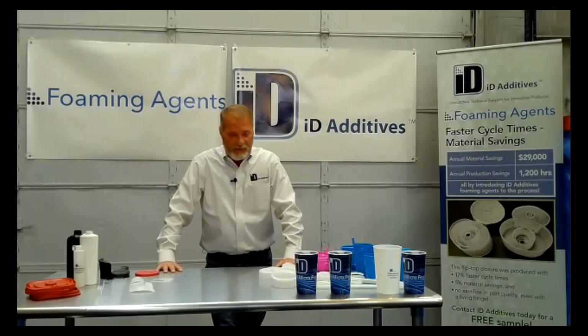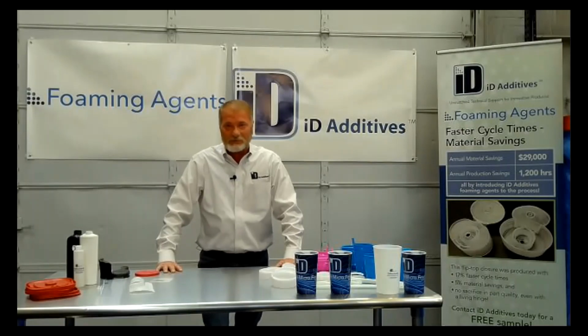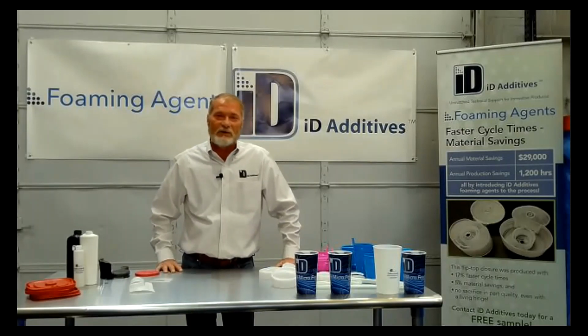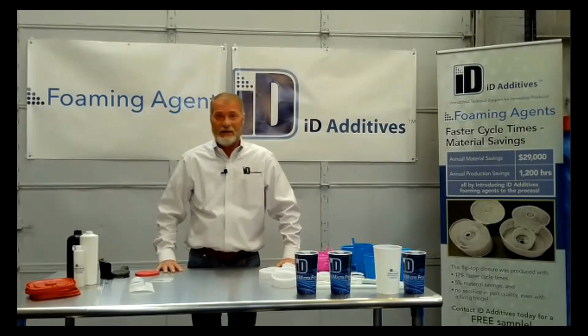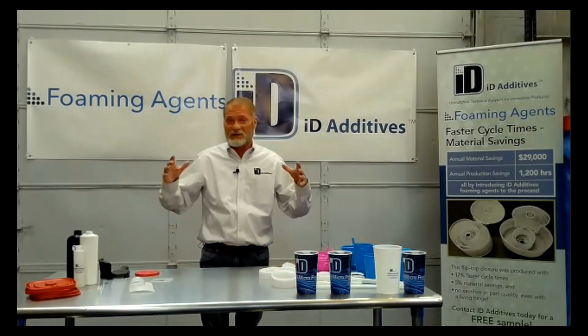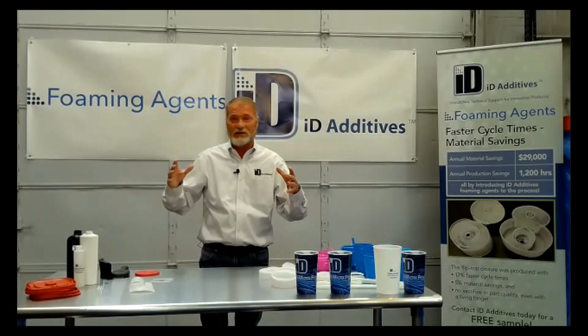And in extrusion blow molding, I guess the key to that is temperature and pressure. And I'm talking about blow pressure. Blow pressure is like adding pack pressure. If you got it too high, it'll pack all the gas out of the sidewalls and you won't have anything. And as it comes out of the parison, the viscosity has already changed.